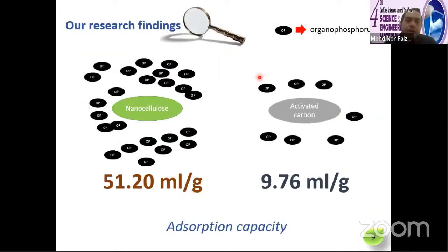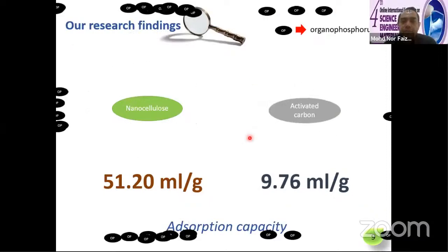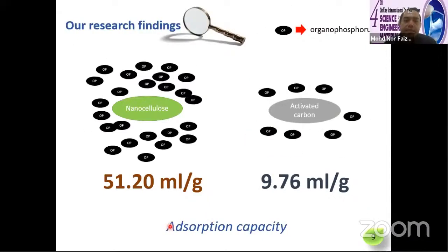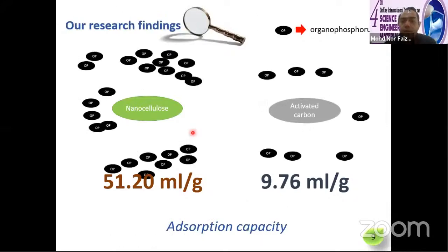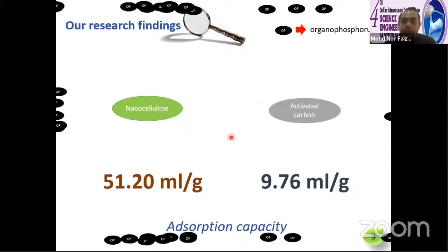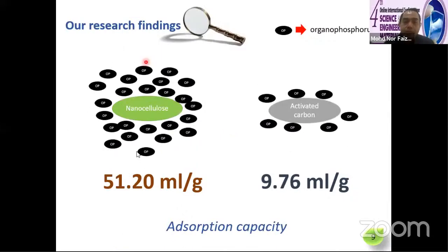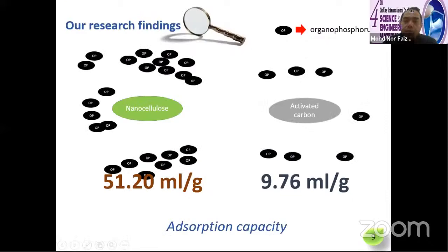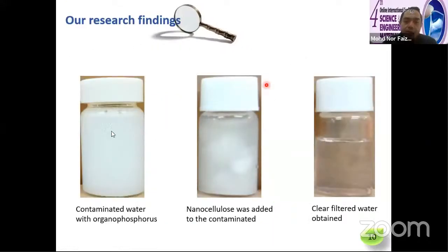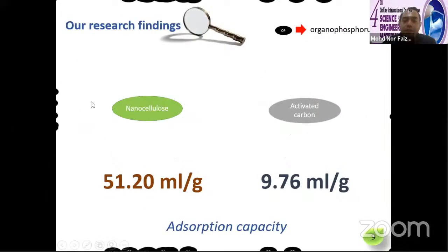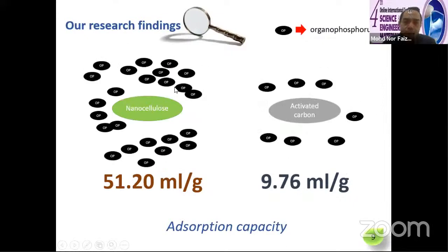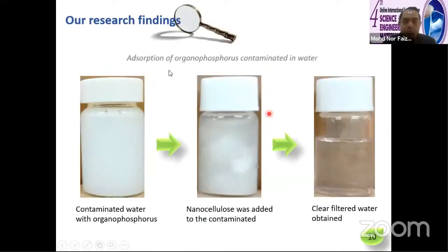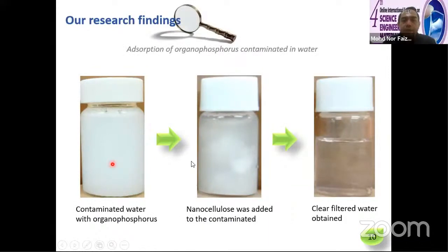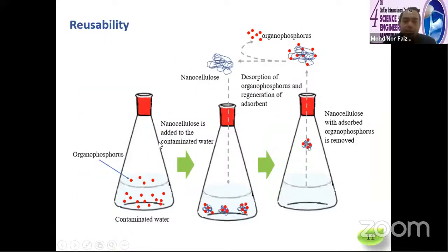My team has also studied the adsorption capacity. Interestingly, as we can see here, the nanocellulose has five times higher adsorption capacity compared to the activated carbon. So it proved that the nanocellulose, without any modification, has a good ability to be a material for filtration of organophosphorus. And this slide also shows an example of another finding, the capability of nanocellulose to adsorb organophosphorus.